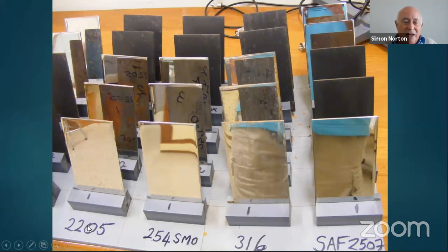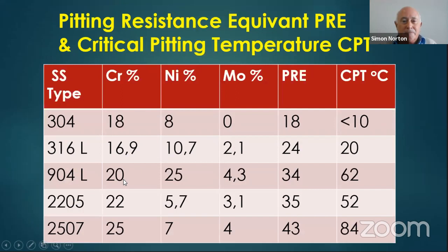has been carried out. If you look along the bottom, you'll see we used DUPLEX 2205, we used super austenitic 6% molybdenum 254, we used austenitic 316, and we used another super DUPLEX, SAF 2507. And then we've got different coatings and mirror finishes, and we wanted to see whether we could get away with a high mirror finish but a much lower cost stainless steel. In the end, we went for the DUPLEX 2205, and in practice, it was highly successful.